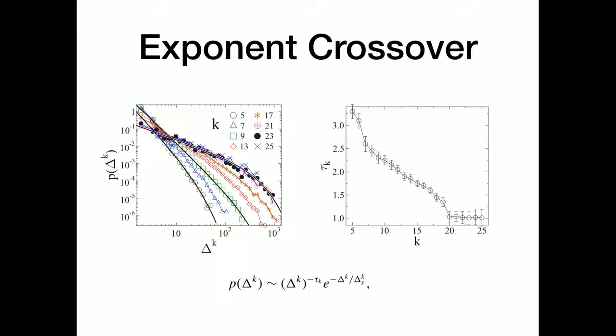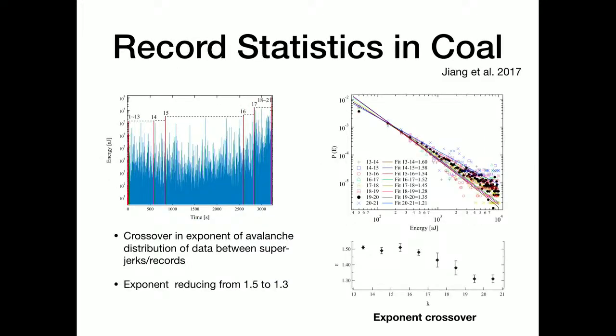the statistics of that shows that there is a change of slope in the power law behavior, and that has been summarized here, that from a high value to a low value, this is now what is off critical. Earlier off critical was this entire thing, the entire data. Now we are even splitting it for each, between each records. And similar record statistics in coal has also been shown to result in the exponent reducing from 1.5 to 1.3, and this is all experimental data where you see this transition from the exponents of the subsequences at lower k to higher k.